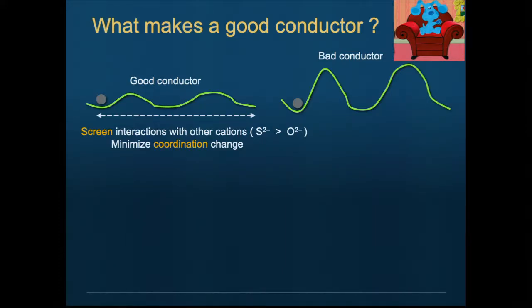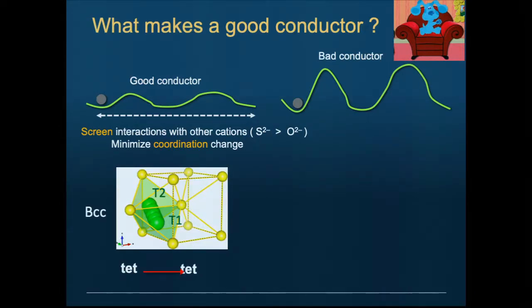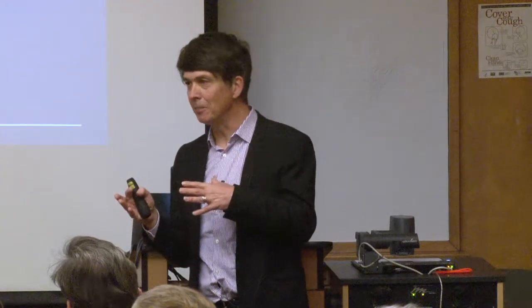The diffusing ion, like lithium, also gets a lot of its energy from the coordination by the anion, right? So as it changes its coordination, it's really changing its electrostatic energy from the anion environment. So you really want to minimize coordination change as you diffuse. And that was a key insight, because we started looking at different packings of anions, and something that you probably teach in freshman material science became suddenly very important, that if you look at BCC versus FCC, they have very different interstitial voids counting.